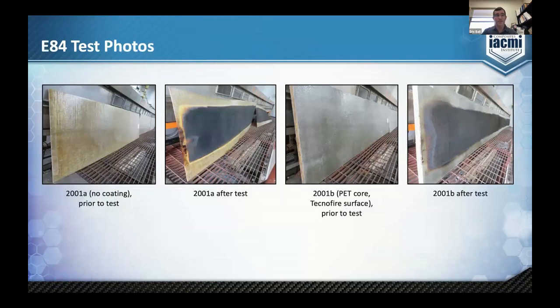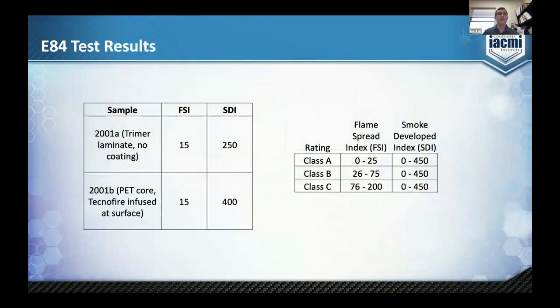So there's the test results. There on the far left is the panel with no coating, and the third one over here is the one with the Tecnofire on the surface. And of course, you can see after the test the burn marks there. This was kind of interesting. The laminate with no coating had a flame spread of 15, but a smoke development of only 250, whereas the Tecnofire had a smoke development of 400. And that's because the Tecnofire has to burn in order for that intumescent to work, and it added to the smoke. So if we're just looking at straight E84 results, the trimer resin with no Tecnofire would perform better. But as you'll see later, that Tecnofire is important when we look at the E119 testing.